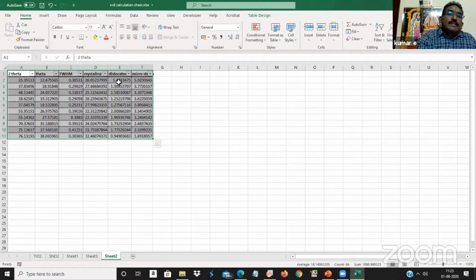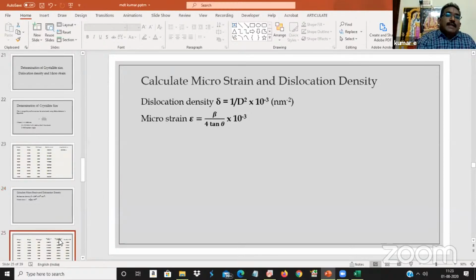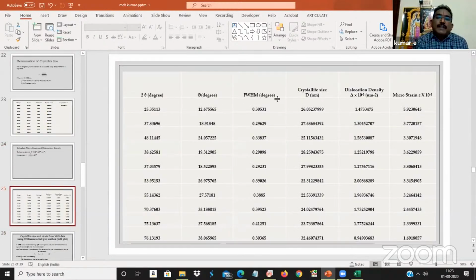So now we calculate the dislocation density, delta is equal to 1 by d square. We substitute the value for d, the size of the nanoparticle, and we get the dislocation density. Similarly, to calculate the microstrain, epsilon is equal to beta by 4 tan theta, where beta is the full width of maximum, theta is here. So by using this, we get the microstrain. So we tabulate the 2 theta value and full width maximum value from the Origin graph, use the Debye-Scherrer equation to calculate the crystallite size, then use this to find the dislocation density and microstrain.